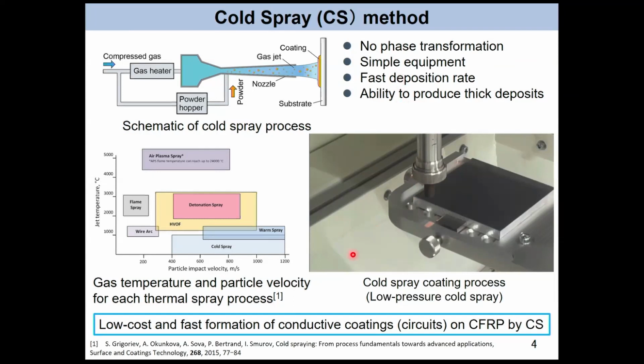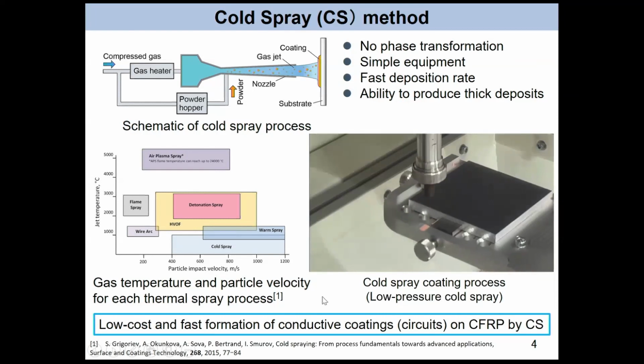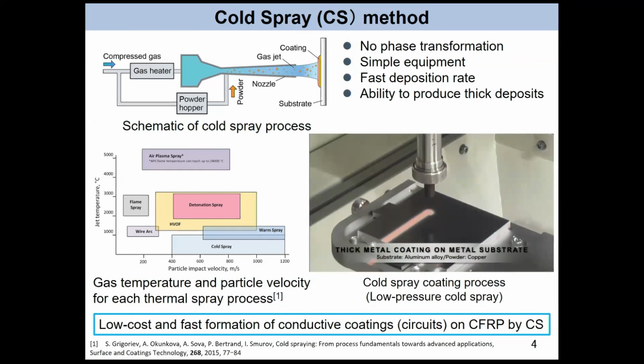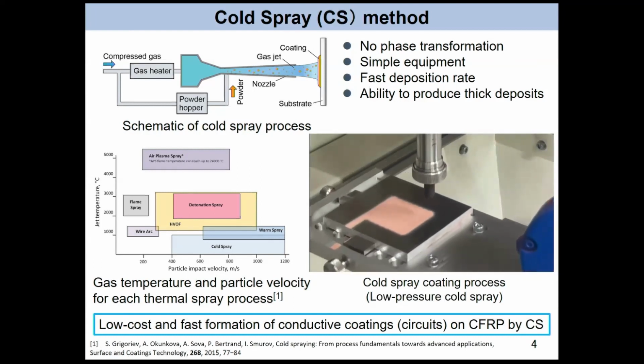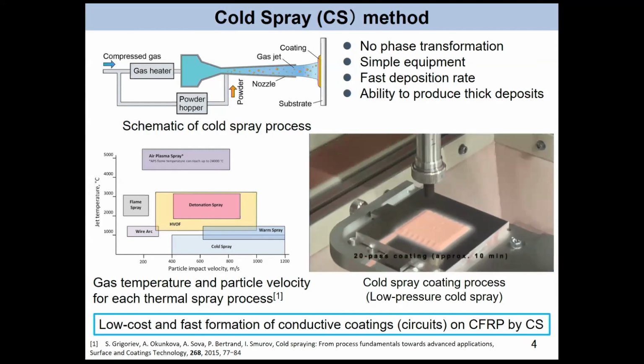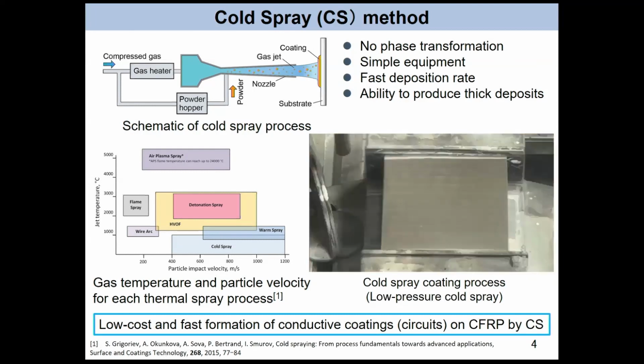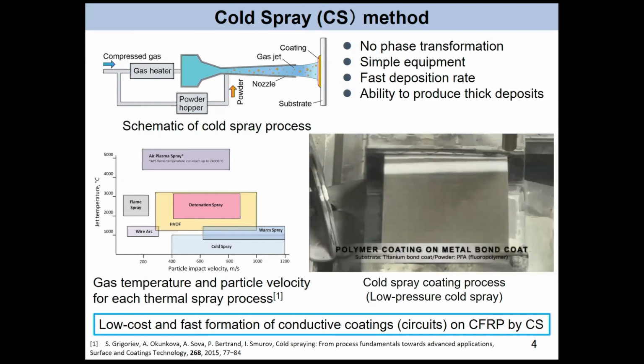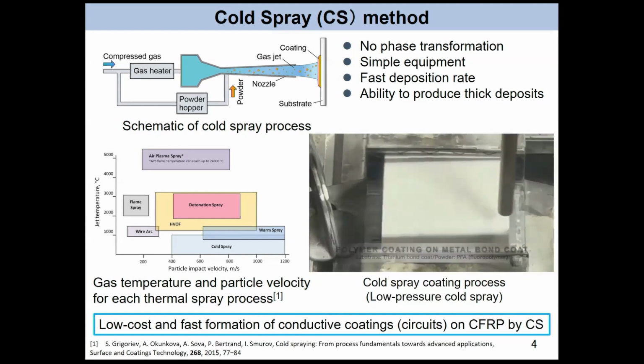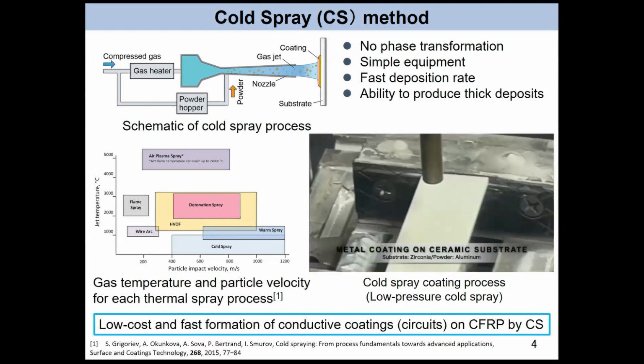So let me play a video of the actual cold spray process. This is a metal coating on a metal plate. This is copper particles on an aluminum alloy substrate, a normal metal-on-metal process. And this is a polymer coating on a titanium bond coat, so a polymer coating on a metal substrate. This is dissimilar material deposition. And also this is metal deposition on a ceramic substrate. We can get a cone-shaped structure in a short time. This cold spray technique is, I think, very suitable for metal formation on CFRP. So this is an attractive candidate.